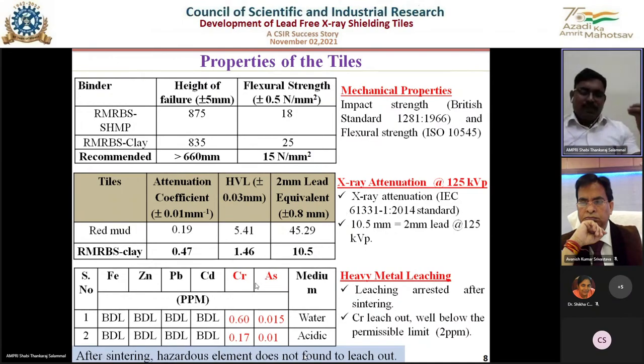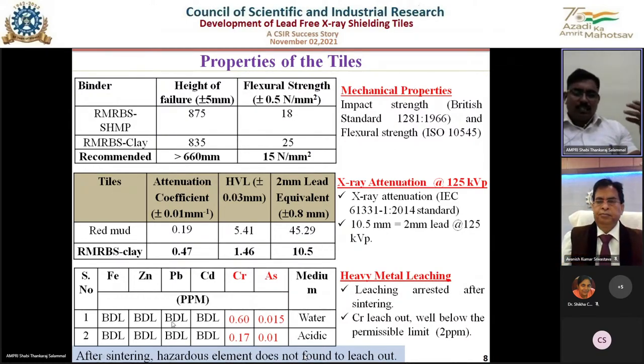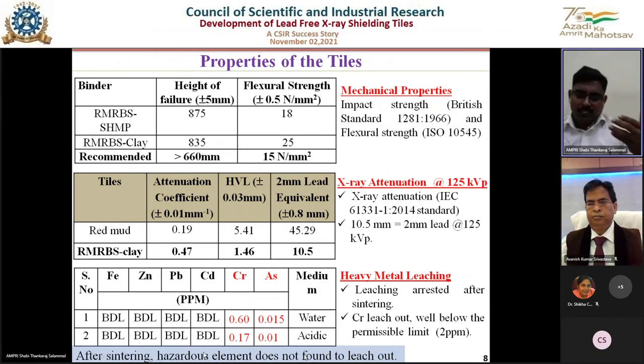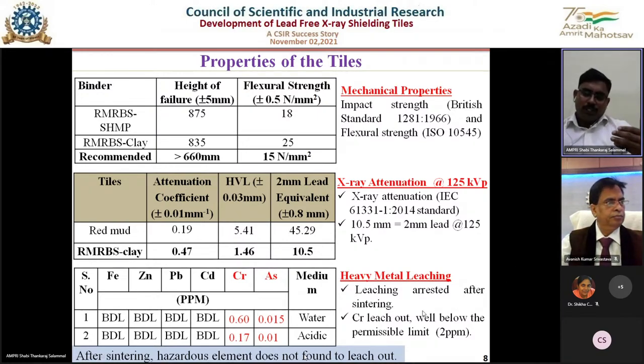So we have tested for lead, cadmium, chromium, and arsenic after sintering. From these tiles, lead and cadmium were not leaching out, well below the detection limit, that is well below the ppm level. But chromium and arsenic were leaching a little, but still they are well below the permissible limit. For example, chromium is 2 ppm and arsenic 0.2 ppm. So they are well below that.